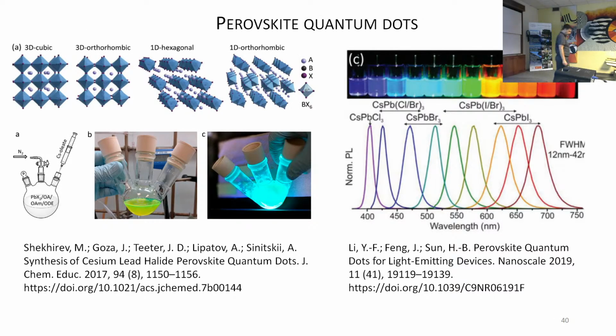We started to do perovskite quantum dots because it was a hot topic during that time, it still is, and they looked very easy to produce. At least in 2017, there is a paper in Journal of Chemical Education that seems that it is something very easy to do. It's not easy. We took at least 1 year to synthesize this quantum dot. It was much more tricky because it's easy to produce the quantum dots. The problem is that, yes, you have very bright luminescence for 30 minutes, because then they have the degradation and they disappear. Okay, so to make stable quantum dots was a real challenge.